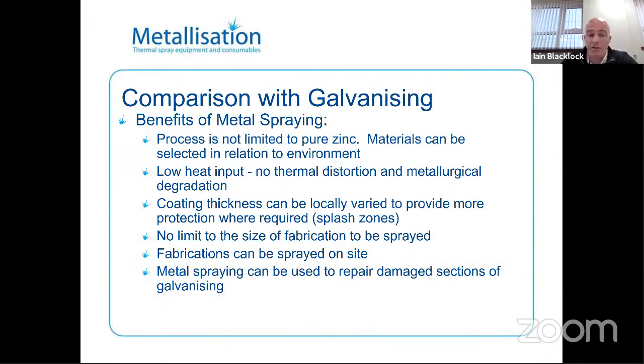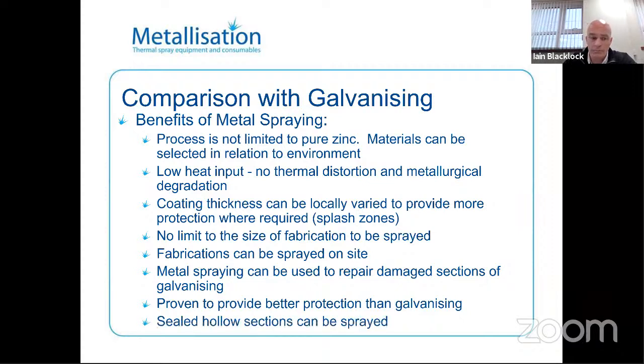Metal spraying can be used to repair damaged sections of galvanizing. Again, it was touched on by Mike with regards to the paint. The same with the thermal spraying. Thermal spray zinc is the most comparable galvanizing repair because it is a pure zinc coating. So preparing the damaged area of the galv, grit blasting it, and then applying the zinc will give you equivalent corrosion protection, if not better if needed. It's proven to provide better protection than galvanizing.